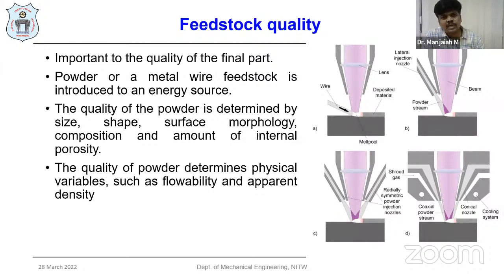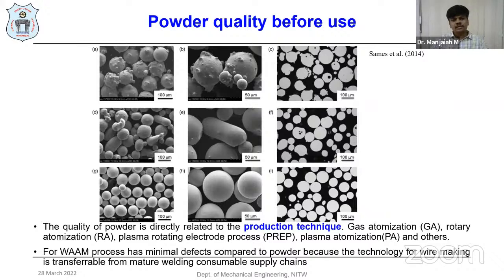The quality of powders is determined by size, shape, morphology, composition, and how much internal porosity exists in the powder. This directly relates to the quality of the component manufactured by the AM process. If you see the powder quality here, the powder has a very rough surface with satellites and some internal porosities. This is the magnified view and cross section showing the internal porosities. In another, the powder surface is finished, but some elongated irregular shapes and porosities are there. And other powders are very spherical, with a very smooth surface finish and no porosities.